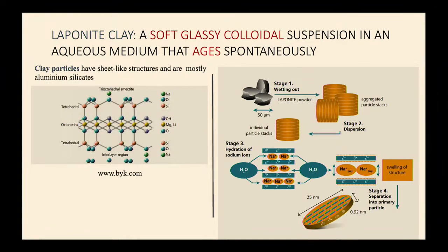As a result of this, the sodium ions in the interlayer gallery try to come out into the bulk, and as a result, the clay swells. Like I told you, each clay particle has this double layer repulsive layer around it. Because of the swelling of the clay, when the double layer repulsion exceeds the interparticle van der Waals interaction, the clay particles start peeling off from the edges. This is called exfoliation.